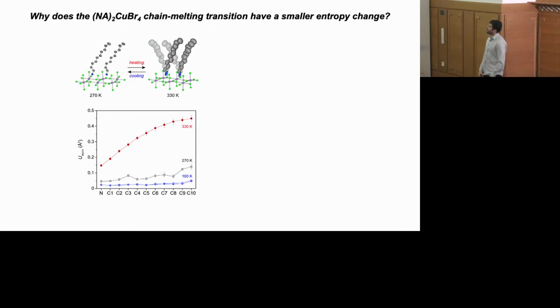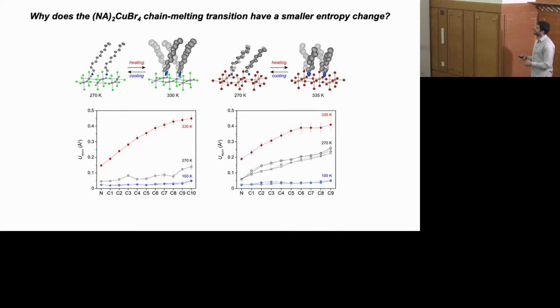And the reason we think that this material undergoes a phase transition with much lower hysteresis than the previous material I discussed has to do with the fact that we're adding in these larger bromide anions compared to these smaller chloride anions. This increases the cavity size of where the ammonium group of our alkyl chain is sitting. And it leads to slightly more disorder that's present in the lower temperature phase of this material.